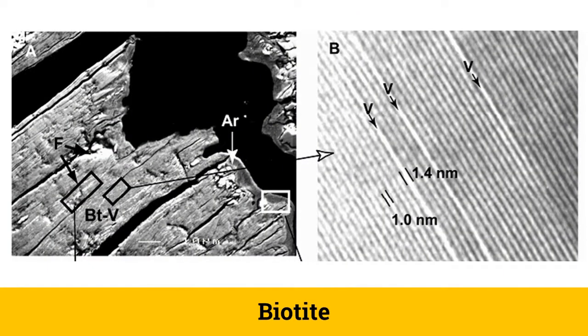The image to the left is a microscopic image showing the foliated structure of biotite, a black-colored mica mineral. The other image is a transmission electron microscopy image which shows the parallel arrangement of TOT layers spaced 1 nm apart. The opening of layers marked by 1.4 nm shows the beginning of splitting of mica sheets in biotite.